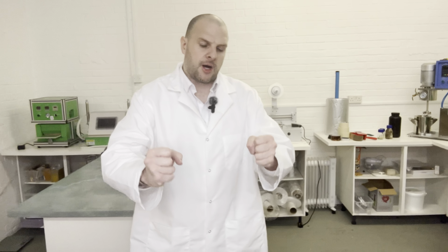Right, the results are in and I'm very excited. So let's give a summary very quickly of the results. Okay, I need to calm down. So 550 degrees with our paint, with our graphene additive, stood up, and there's no blemishes, no bubbling, no damage, and I'm really, really excited by the results. The one that did not contain graphene obviously bubbled up and it's very distorted, and we had a few close-up images, but at the very end of the video I'm going to add some imaging so you can actually see a like for like. But it's very, very clear that the graphene offers maximum protection for the car paint.